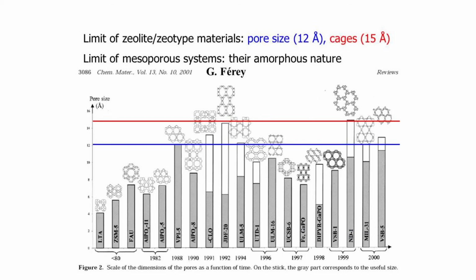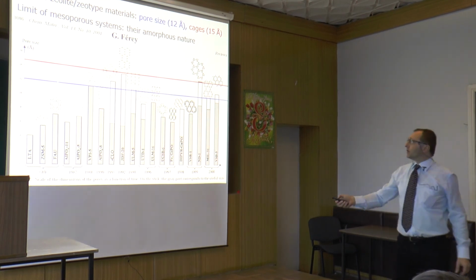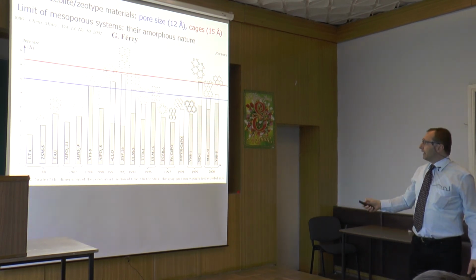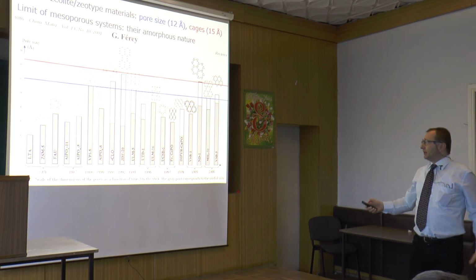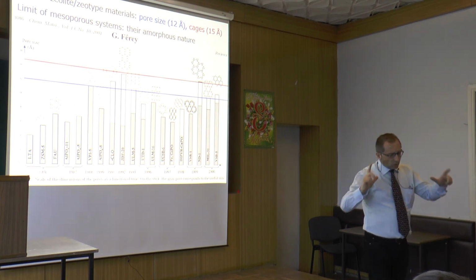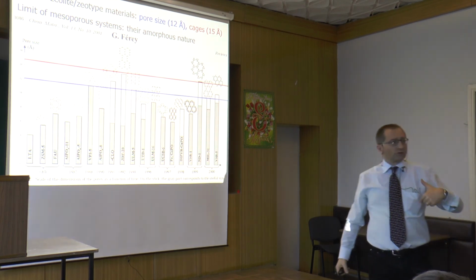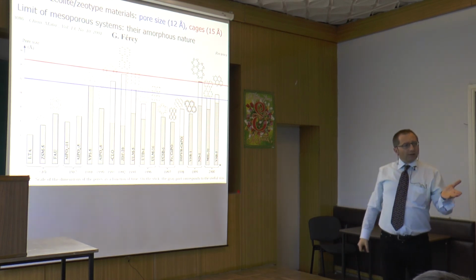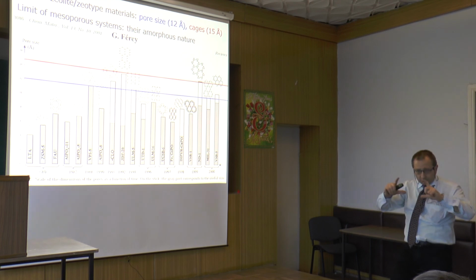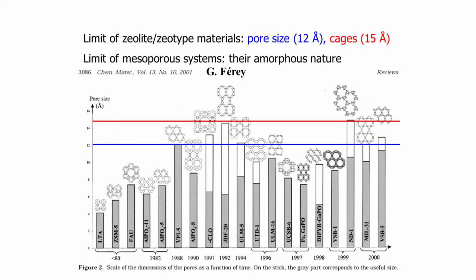The point is that this is a selection of zeolite types, and the problem of zeolites is that they have an upper limit in the cage dimension, which is close to 15 Angstrom, and a more dramatic limit of 12 Angstrom for the pore size. This means that if we want to make catalysis, or use these as molecular sieves, the molecules that can be selected by these pores must be smaller than 12 Angstrom. If we want to work with bigger molecules, we cannot do this job with zeolites.